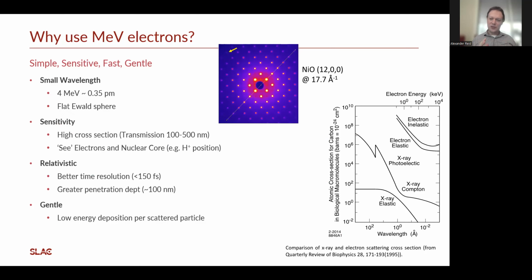And one of the reasons for this is because of this high energy. Because we're dealing with MeV electrons, we have a very small wavelength. The wavelength is very much smaller than the separation of the atoms. And this means that we actually have a very flat Ewald sphere. It means that we're getting a very flat slice of momentum space. And so here, for example, for a nickel oxide diffraction pattern, we can see peaks going all the way out to at least 1200. And we're getting a lot of information from all of these different peaks in one single measurement.